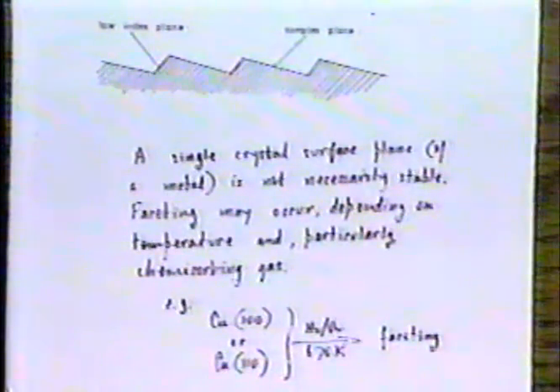Considerable energy is generated locally on the surface, and this locally generated energy is enough to cause atomic mobility. Under oxidizing conditions the oxygen is usually adsorbed to some extent on the surface of the metal, and the oxidized surfaces have their free energies changed by comparison with the free energies of the virgin metal surface in a manner that makes the faceted structure more stable thermodynamically than the initial flat structure from which it was formed.